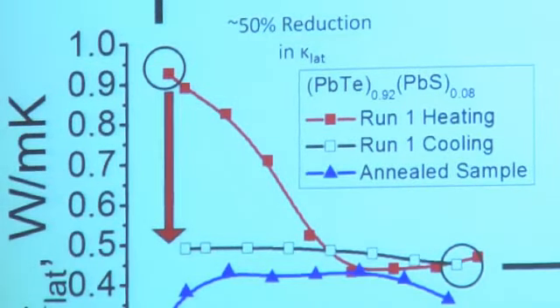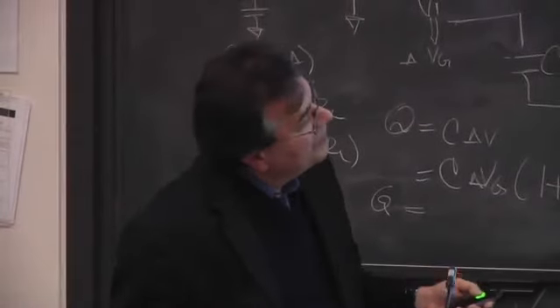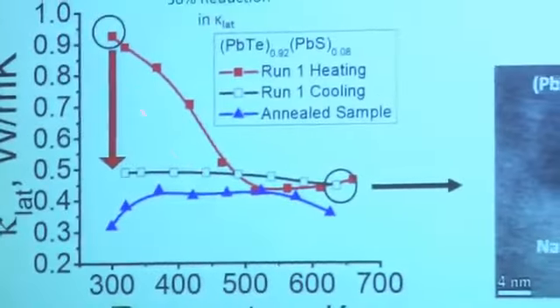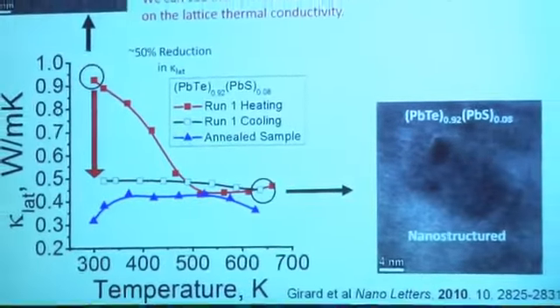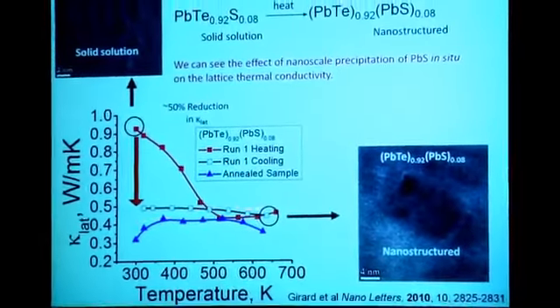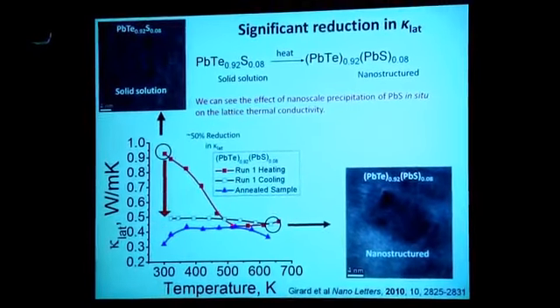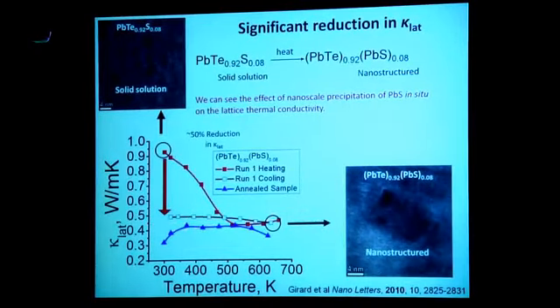So that's this disorder, this alloy scattering works very well. However, when you raise the temperature and these things begin to form, the thermal conductivity collapses by another 50% into this area, well, 0.4 to 0.5. And then it stays like that in subsequent cycles. So to us, this proved that it is the nanostructures that actually are scattering these phonons very effectively.